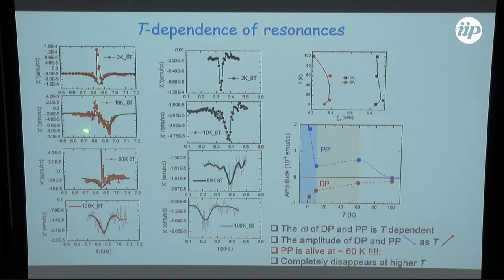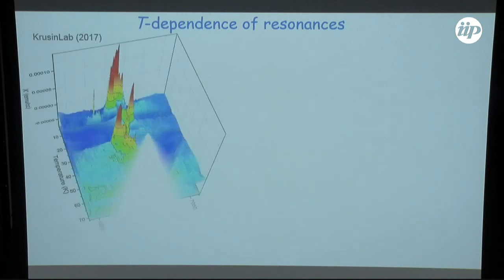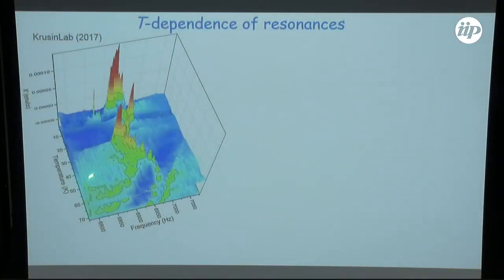And at our global coherence temperature, something happens. In zero field, the paramagnetic peak and diamagnetic peak just violently split. And let me just show you how it looks on a better scale. So now again, this is chi prime. This is temperature, this is frequency. This is where we saw the global coherence achieved, and where this paramagnetic peak basically kicks out. And at the temperature where we see the mesoscopic Meissner effect, this paramagnetic peak basically bifurcates and levels off